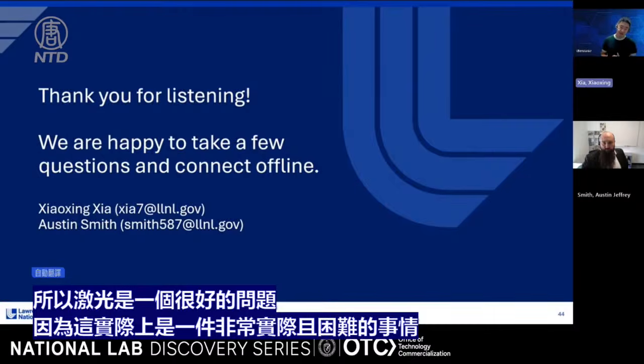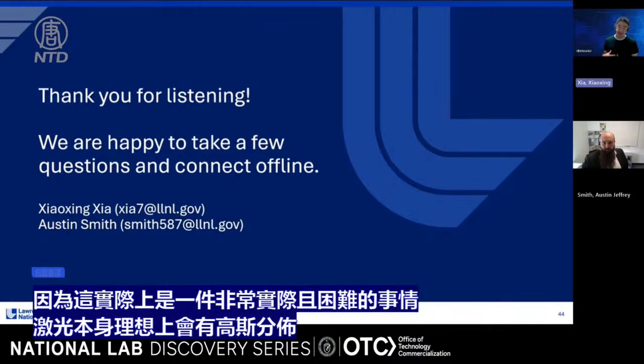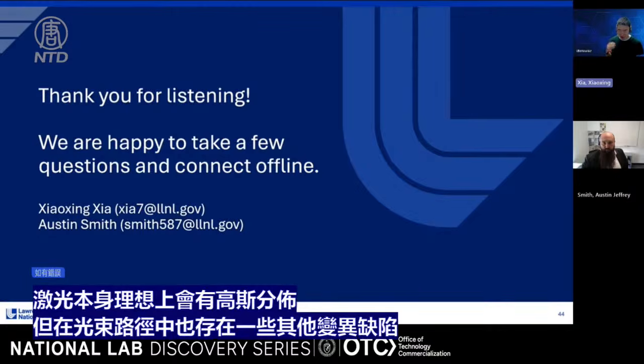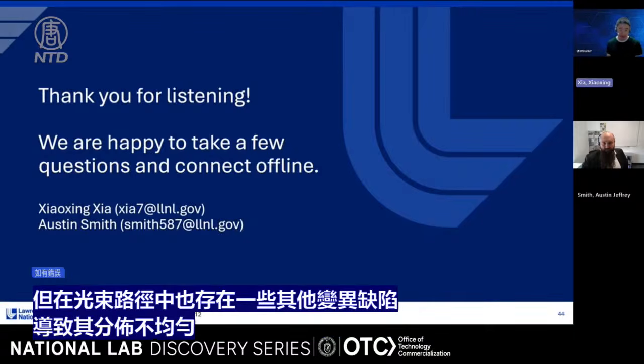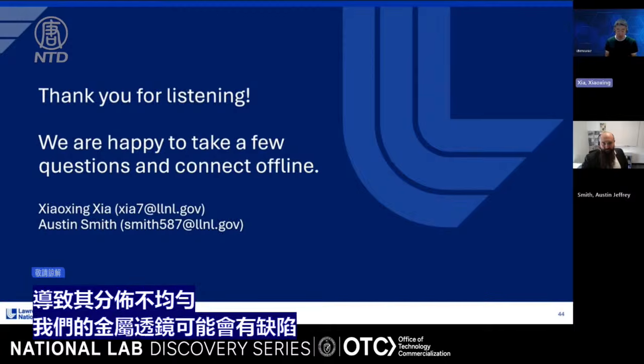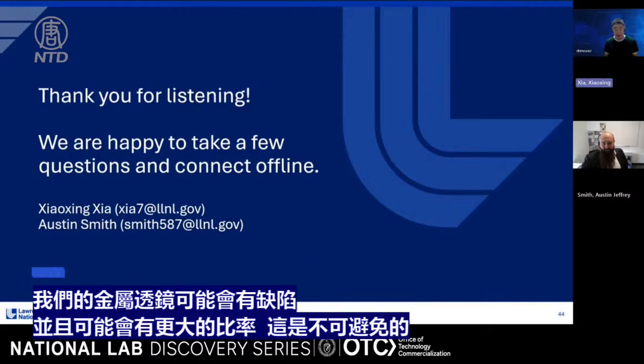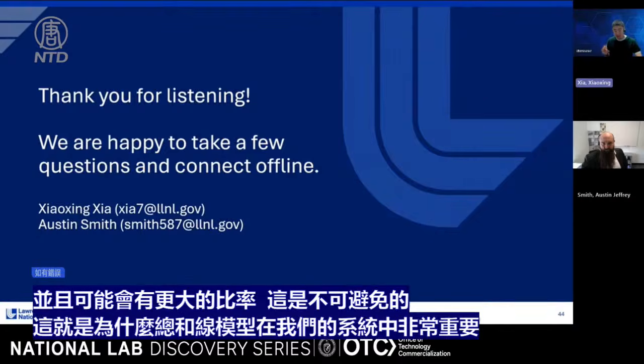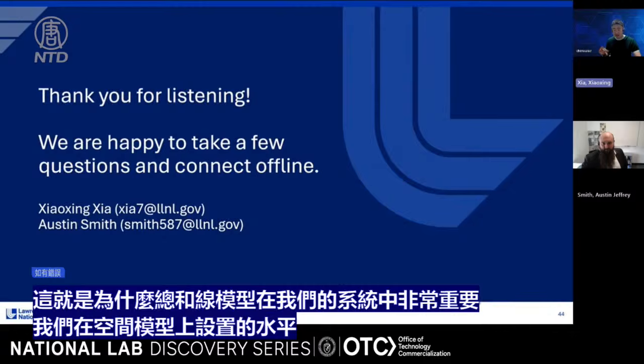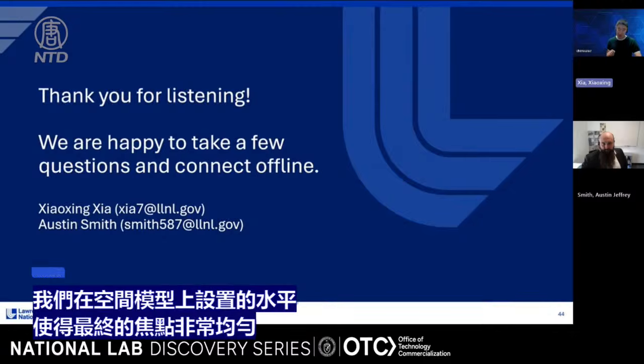So the laser is a very good question because it's actually a very practical, difficult thing to do. The laser itself will have a Gaussian distribution, ideally, and there will also be some other variation and defects in the optical beam path that give it a non-uniform distribution. And our metalens could have defects. When you have a larger array, inevitably there will be defects. So that's why the spatial light modulator is very important in our system. We set the levels on the spatial light modulator such that the final focal spots are extremely uniform.